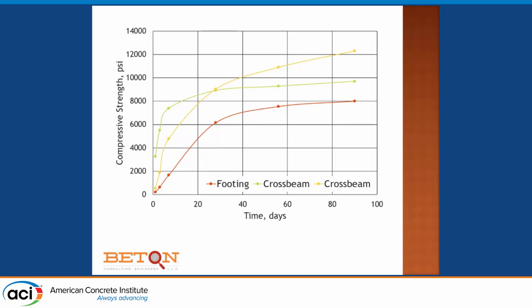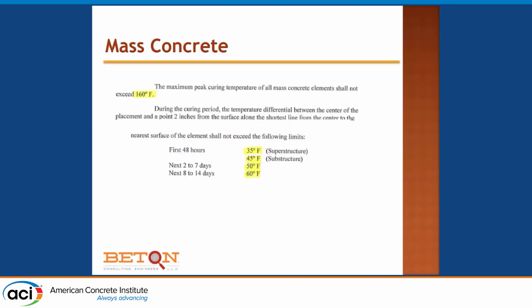And this is where we dealt with MnDOT and said, listen, the issue here isn't what the cylinders break at. Who cares? You're not going to post-tension the cylinders. The issue here depends on how hot these members are and what their maturity is. At a clock time of 18 hours, how mature are they? So we built a maturity model, and with that maturity model, we were able to predict what the strength would be and then confirm it using match cure cylinders. Now, MnDOT requires you to update your maturity model every 2 weeks. Small steps. So we'll see. It's only been around since Nurse and Saul did the work in the 50s, right? So we're not sure. After it comes up to a century, we might be okay, but they're never sure.